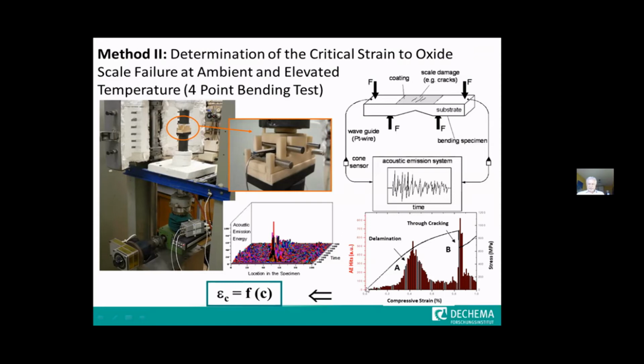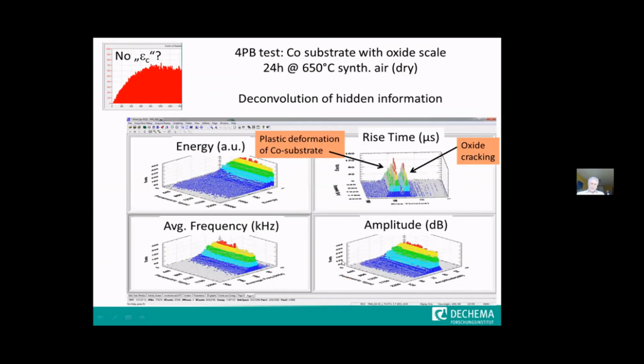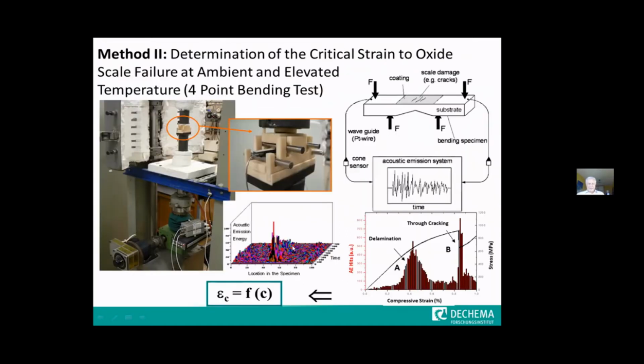That is, this is compressive strain here, of course, usually you can do it also under tensile strain. So after a while, the number, in this case, of acoustic emission hits starts to increase strongly. And this is usually the case when you have large-scale cracking going on in such an oxide scale. And by locating the signals, you can also find out where it actually takes place, and you can correlate this also with the local strain on this 4-point bending bar.